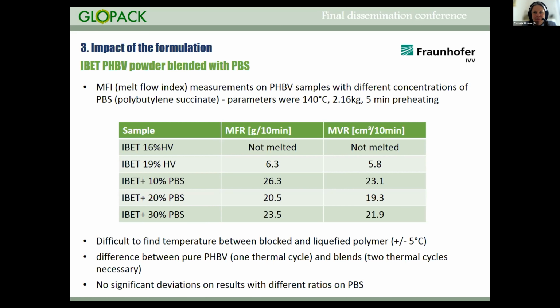Yeah, and as Hélène mentioned, in the last run with the project material, we blended the PHBV with PBS, polybutylene succinate. And the blend material we then used for injection molding. And before, we measured the melt flow index from the compound to estimate the processability. This index, the melt flow rate, is used to characterize the flow behavior of a thermoplastic polymer at certain pressure and temperature conditions.